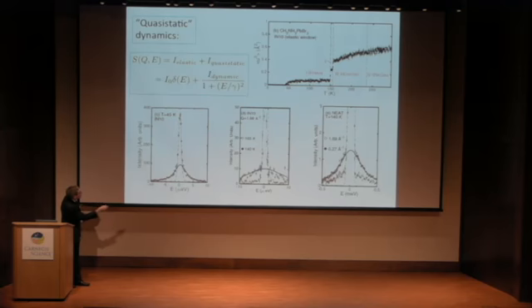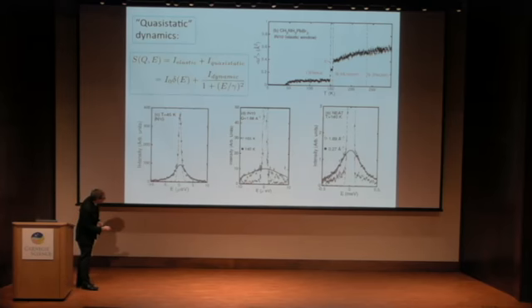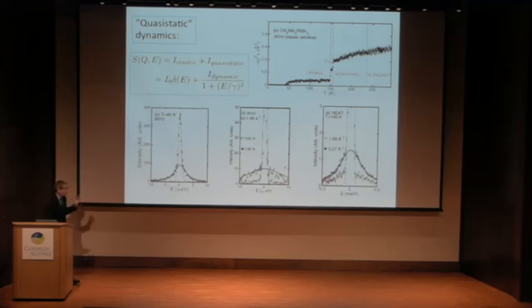Now, if you march up here towards the first phase transition at 140, those are the solid points here. This is the same scan taken on IN10, the backscattering spectrometer, and you see that there's actually no observable scattering. If you heat up a bit into this intermediate phase, you do see a dynamic component that, again, recovers. However, if you keep going, you find that the dynamics leave the time window of the spectrometer.